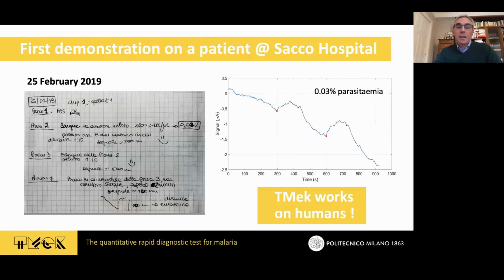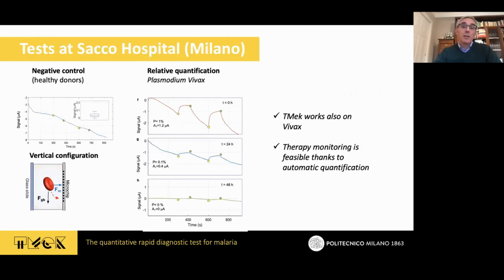And this is just the first measurement we carried out on a patient affected by malaria at Sacco Hospital. You see the characteristic line shape that we have seen. That was the first experiment, February 2019, showing that it was working also on humans, not only on models. And at Sacco Hospital, we obviously made some control experiments on healthy donors, showing that in this case, there are no jumps. You see that when you move the magnet, there is no signal change here.